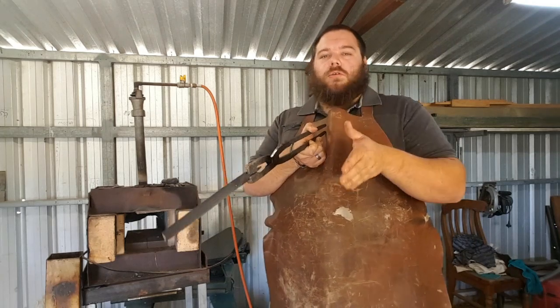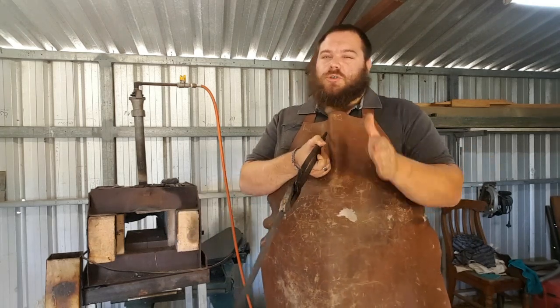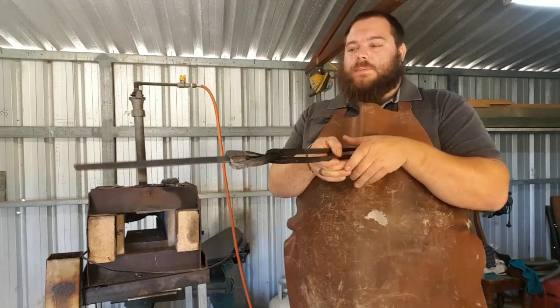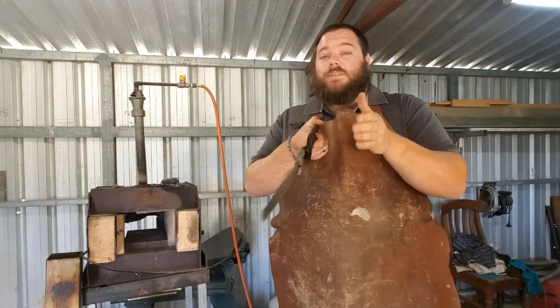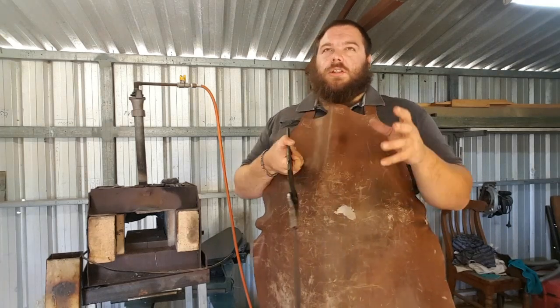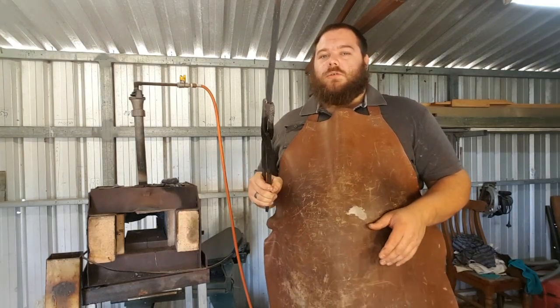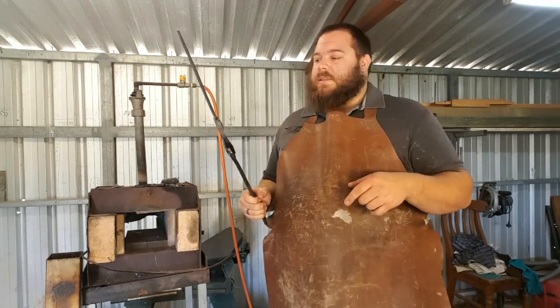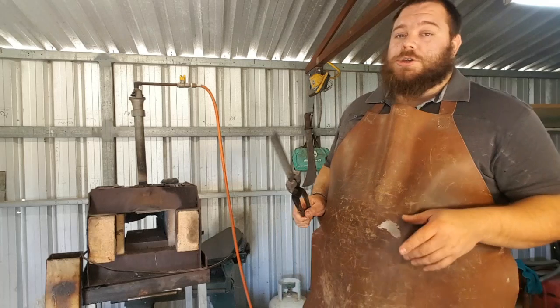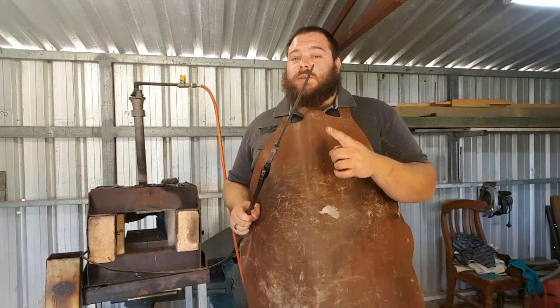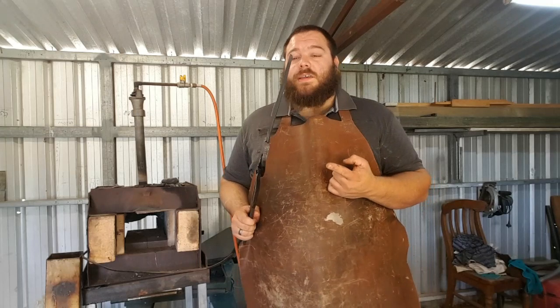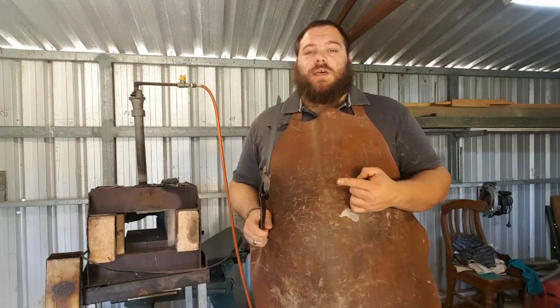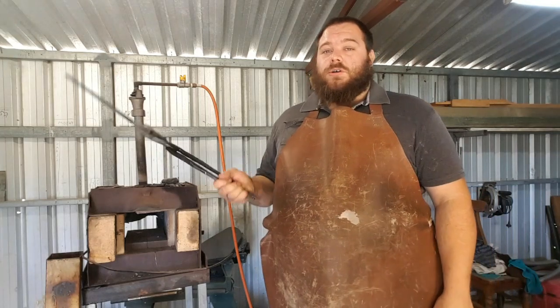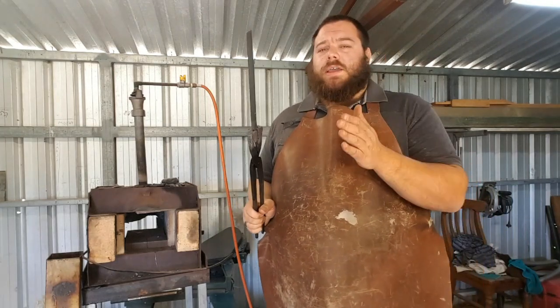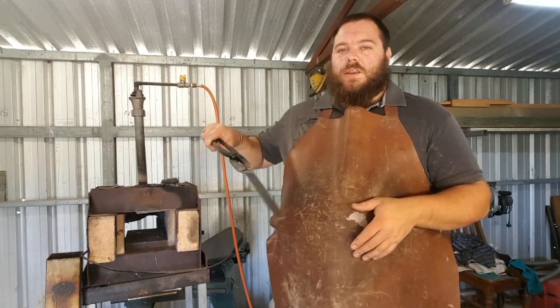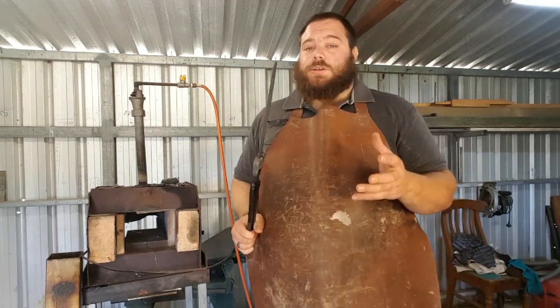That's why when you're pre-grinding, if you're grinding before heat treat, you need to make sure everything's nice and even and flat, because any discrepancies are going to cause warpage. And this is warping during normalization, which is something that a lot of people don't talk about. A lot of people talk about quenching, and they say you've got to be careful of warps during quench. Sometimes the warp will happen during the normalization cycles, and people don't notice because they're not looking for it. All they're doing is putting it on top of their forge or whatever. They're not really looking at the piece of steel. And then when it comes to the quench, they go, oh no, it warped in the quench. It may have actually warped during normalization.